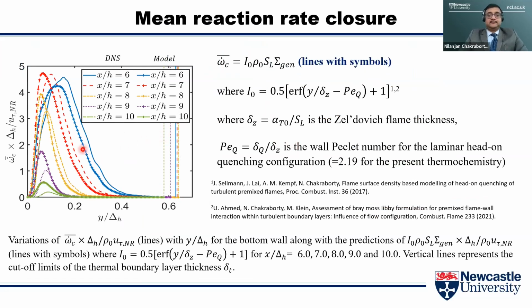Here I am showing the reaction rate closure that I mentioned earlier. The first thing to note, these vertical lines are the edges of thermal boundary layer. So first thing to note that the reaction rate actually takes place within the thermal boundary layer. What happens to the model performance? It does reasonable job away from the wall, but as soon as the quenching starts, there is quite a bit of discrepancy. Please note this model was proposed for head-on quenching, and here we are dealing with oblique flame quenching. So obviously, there is a huge scope for improvement of this kind of models for general flame wall interaction.